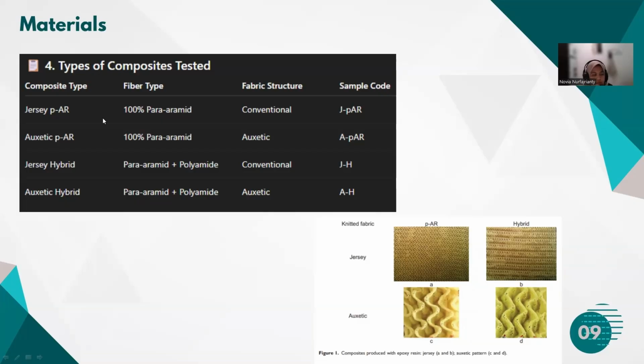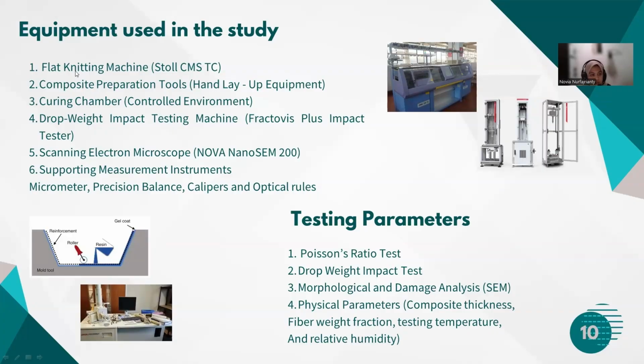Composite test: jersey PAR, fiber type 100% para-aramid, fabric structure conventional; and auxetic PAR, fiber type 100% para-aramid, fabric structure auxetic; and jersey hybrid, fiber type para-aramid plus polyamide, fabric structure conventional; and then auxetic hybrid, fiber type para-aramid and polyamide, fabric structure auxetic. On figure 1, composite produced with epoxy resins, jersey and auxetic pattern.